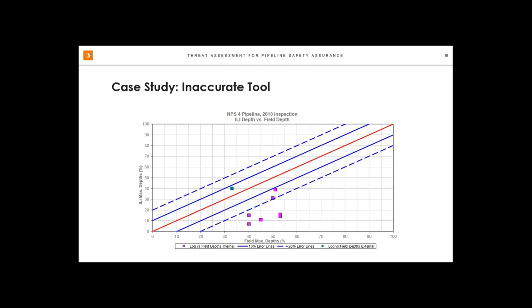So what we determined through our investigation is that this line was suffering from MIC, microbially induced corrosion. It was creating pinholes on the pipeline, which are corrosion flaws that have a very small cross-sectional area. And that was a type of corrosion morphology that this particular form of inspection tool was not able to accurately detect or size. And so the end result was some fairly dramatic undersizing.